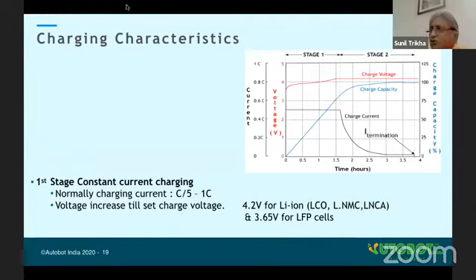Okay, and when you float, the current will start coming down. Now the differential between the charging voltage and the battery EMF is very less, so slowly the current will start going down. And these batteries are not floated. They are not kept on float for all the time to come, not for days together. So there is another criterion, which is the current. Once the current comes to C/40, which means for a 100Ah battery, around 2 to 3 amps, the charging is terminated.